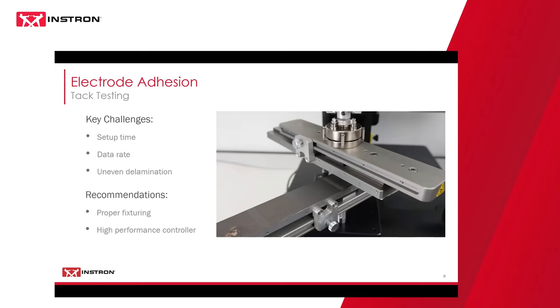One of the key challenges that come from the setup, so for anyone who's tried to set up a tack test before using something like two different platens, it's pretty evident how time consuming and difficult it can be. Since it's critical to repeatability that the contact area of the tack be the same for every single test, an operator must ensure that they prepare the tack on each platen identically and align it properly every single time, which can be very difficult, especially if you have circular platens and a square tack, or any misalignment in the load string. Things like that can be very critical here. This is another prime example of where proper fixturing can help reduce this variability, help reduce the operator dependency, and increase your throughput.